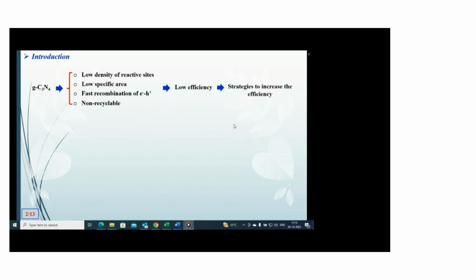However, it shows some drawbacks, including low density of reactive sites, low specific surface area, fast recombination of electron-hole pairs, and non-recyclability, which result in low efficiency under visible light. Some methods have been developed to increase the efficiency of graphitic carbon nitride, including creating a heterojunction that reduces the electron-hole recombination rate. Based on this consideration, in this study, NiCo-ZnCdS/g-C3N4 ternary nanophotocatalyst was synthesized through a simple hydrothermal method. And as expected, this ternary nanophotocatalyst exhibited remarkably enhanced photocatalytic efficiency for hydrogen evolution rate.